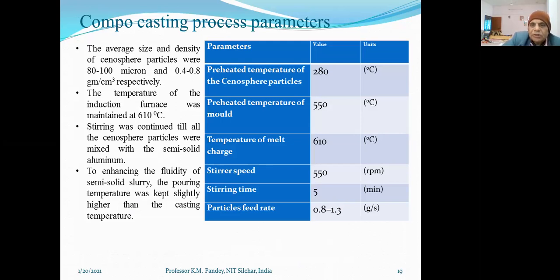So these are the parameters with the values we have set: preheated temperature of the cenosphere particles is 280 degrees centigrade. Then preheated temperature of mold is 550 degrees centigrade. Temperature of the melt is 610. And stirrer speed is 550 rpm. Stirring time is 5 minutes only. And particle feed rate is 0.8 to 1.3 gram per second.